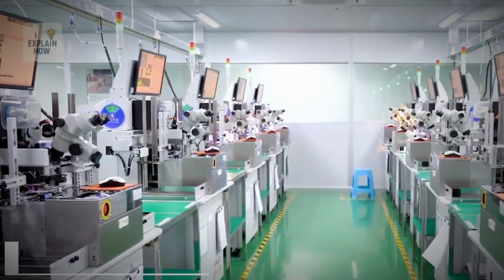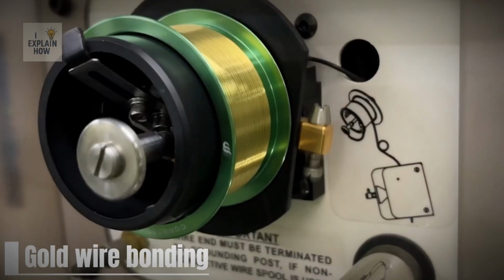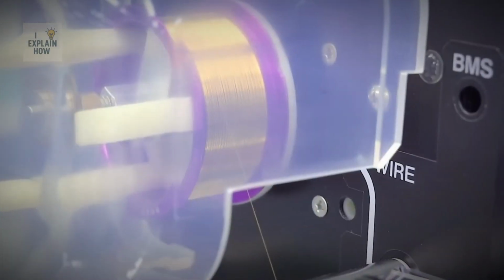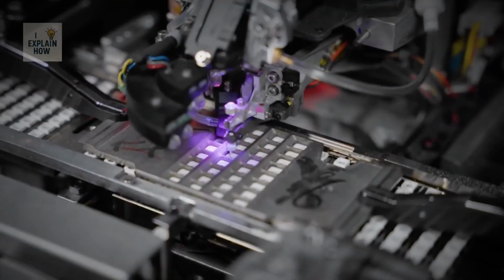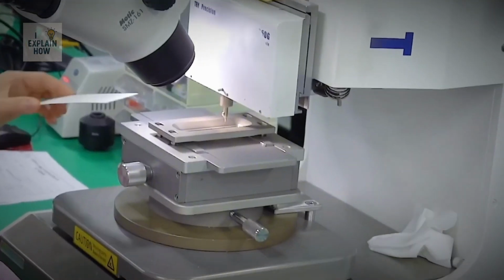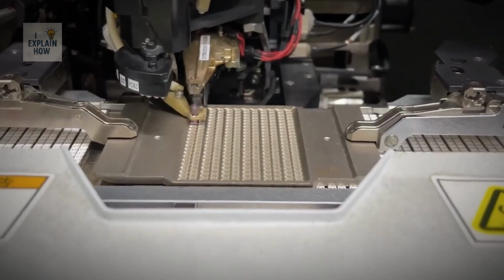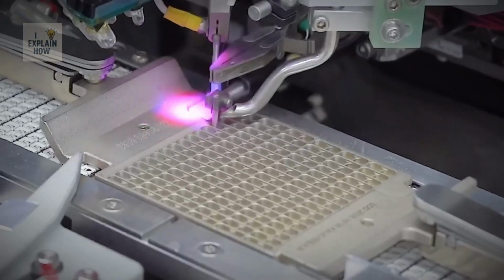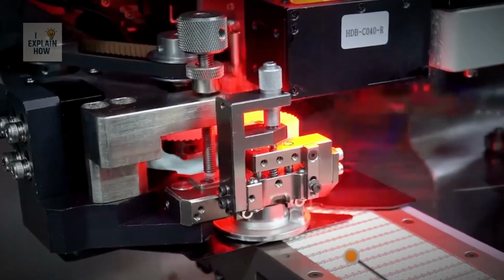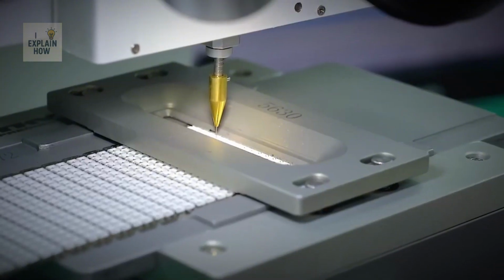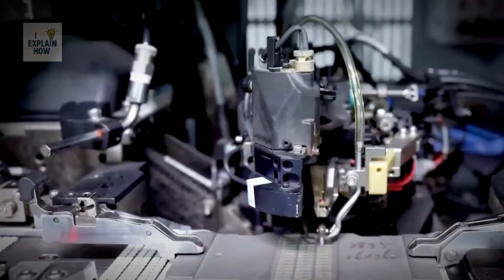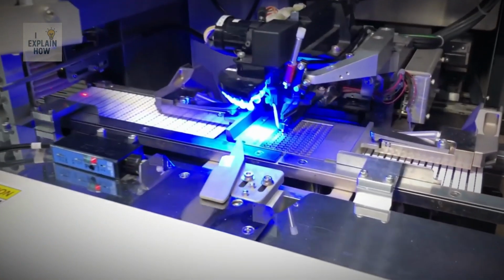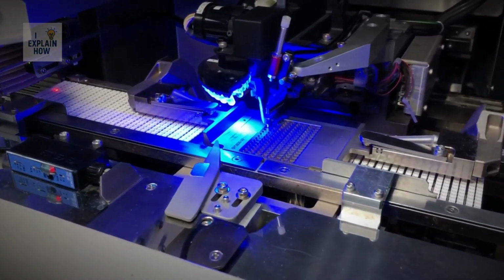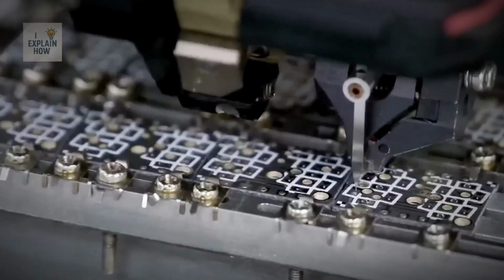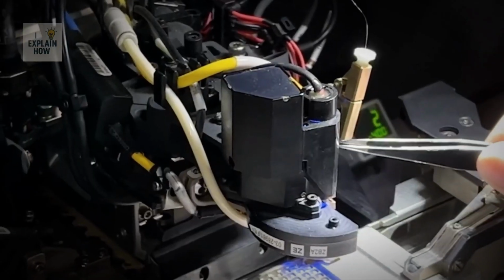After the LED chip has been fully fixed onto the metal conductive frame, the LED tray is transferred into an automatic wire bonding machine. A spool of 99% pure gold wire with a diameter of 18 to 25 micrometers, 3 to 5 times thinner than a human hair, is fed into the system. High-resolution industrial cameras scan each individual chip and its corresponding conductive terminals, calculating their exact position with accuracy of a few micrometers. Using a combination of heat and ultrasonic energy, the machine forms a small gold ball at the wire's end. This ball is pressed onto the chip's electrode, creating the first bond point. Immediately after, the wire is drawn in a carefully formed arc and lowered onto the metal conductor to form the second bond. The wire is then cut and the machine moves to the next chip.